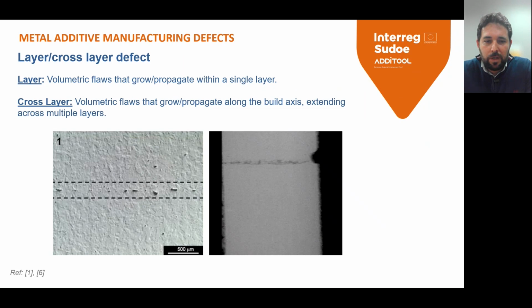Layer and cross-layer are defects that propagate within a layer or along the built-in direction. This defectology could be lack of fusion, cumulated porosity, as you can see in this micrograph. It is cumulated porosity in a layer, and delamination, cracks. This is, for example, a digital radiography image where you can see a lack of fusion produced by a start-stop in the machine.